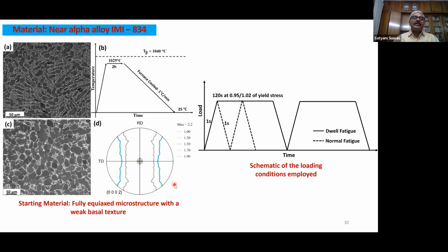Now, the crack nucleation mechanism. For this case, we switched over to the actual alloy. We had enough experience with CP titanium, and then we took a real alloy from the funding body, that is the Indian Defence Organization. So we took this alloy, IMI 834, which is so far the highest temperature titanium alloy used in gas turbines. And we just did some heat treatments. This is a standard heat treatment given before it is used as a forged disc or turbine blade. Generally, it is used for discs.